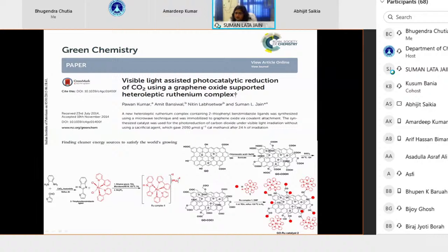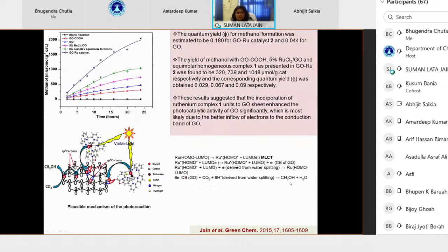Similarly, again, we use graphene oxide as support. Before the immobilization, we functionalize the support for better connectivity or better chemical attachment between the two components. And this is our hybrid system, containing the graphene oxide support with the ruthenium complex highly immobilized on it. So again, if we look at the results,